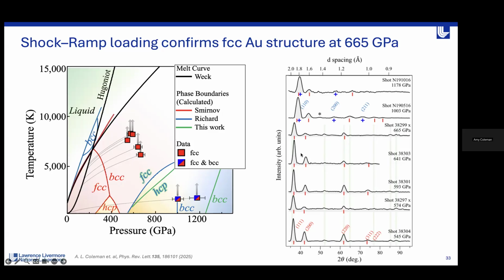The other peaks we have here are from our FCC gold. If you were to use something like an aluminum layer in your package, which we did early on, that causes problems because you'll have peaks overlapping with your gold peaks.